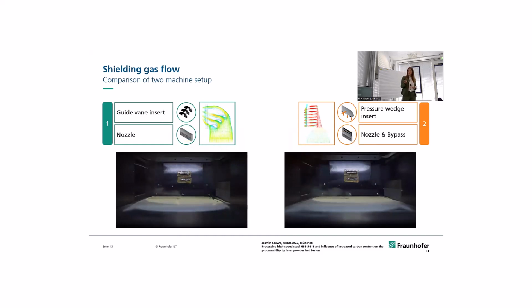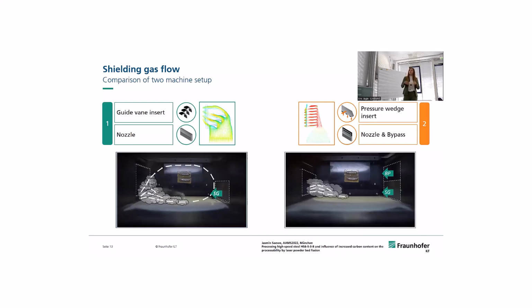So here you can see the setup one that we've used. Here we have a material, it's zinc, so it tends to generate a lot of fume. And you can see that it's not flowing exactly out. You can see there is some fume going up, and then right in the direction where we actually want to manufacture the parts. And here on the right side, you can see with the setup 2 that it is already a little bit or a lot better and less interaction. It's just a schematic if you haven't been able to see it with the contrasts here, but that's how those two setups were working.